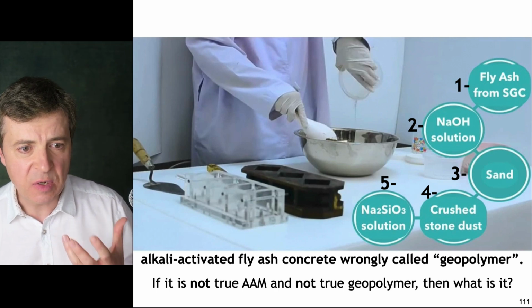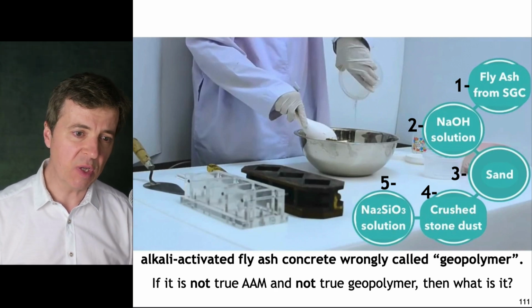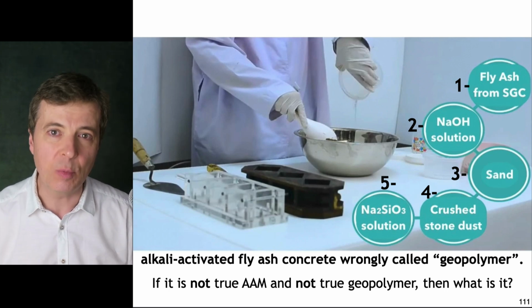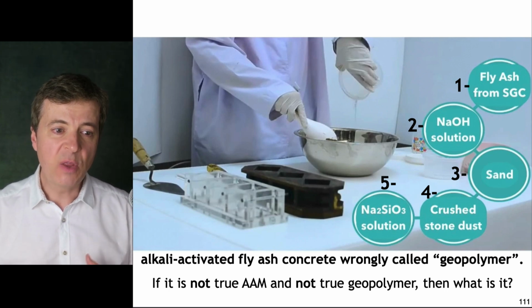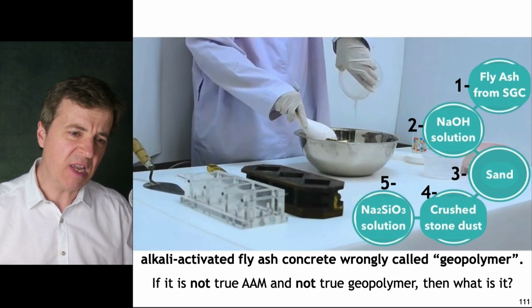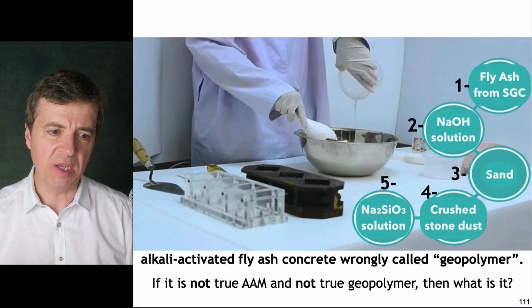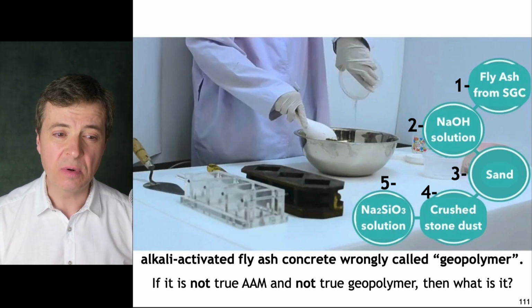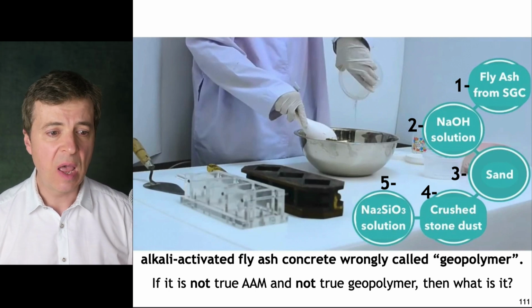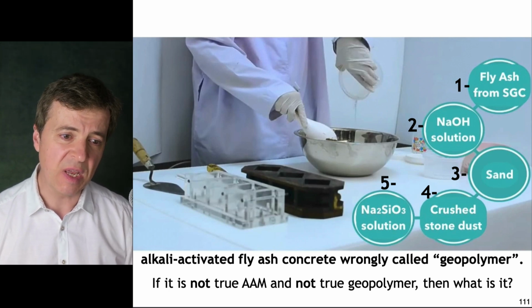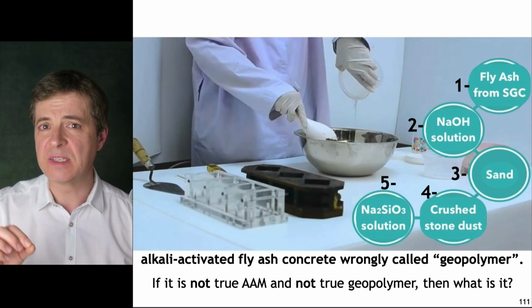This is because sodium is very soluble in water. It is not calcium hydrate, which is insoluble. And it will cause lots of blooming, efflorescence, cracking, shrinkage, and the like. No, this is pure rubbish. It is not alkali activated material, and it is not geopolymer. But in their papers, they use both words as synonyms.